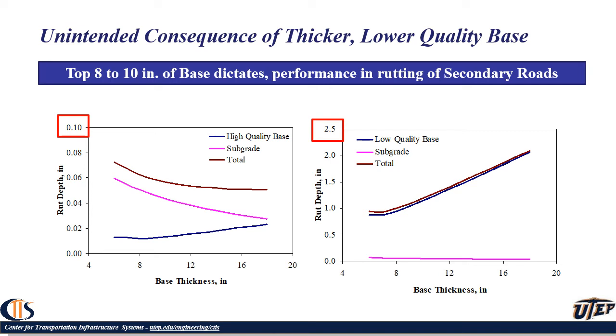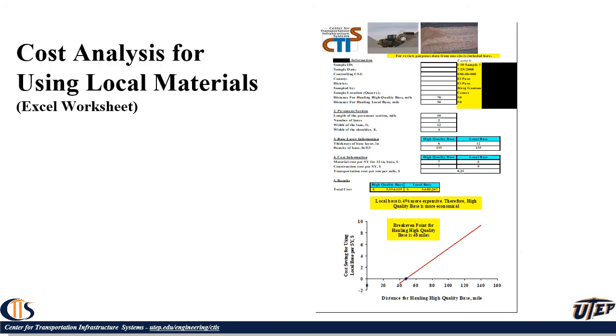But when you look at the thick, low quality base, as we make the base thicker, you're increasing substantially the rutting of the base layer, even though you significantly decrease the rutting of the subgrade. So you should be careful that a thicker base is not the solution. What we found is that the top 8 to 10 inches of the base dictates the performance in rutting of the secondary roads.